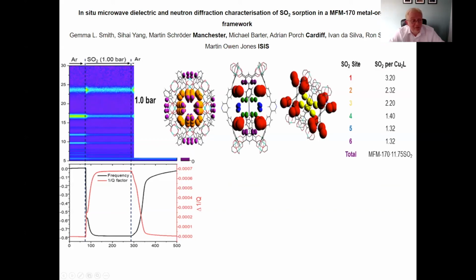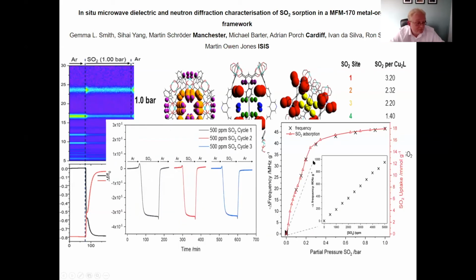Of course, we use this Bragg information to look at the structure and the location of the SO2 molecules within the sites. And we can see that the different sites are populated depending on the chemical potential to bind SO2, of course. And we can correlate that with the dielectric properties as well. So the dielectric properties change depending on which sites are filled. And we can actually get this isotherm. So this is the linear low SO2 part of the isotherm, and the black crosses correspond to the microwave dielectric measurements, and the red triangles correspond to isotherms measured through a normal standard method. And we see the correlation is almost perfect between the microwave properties and the SO2 absorption measured by isotherm.